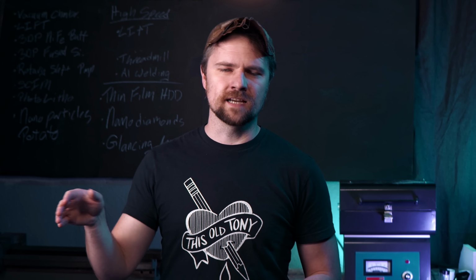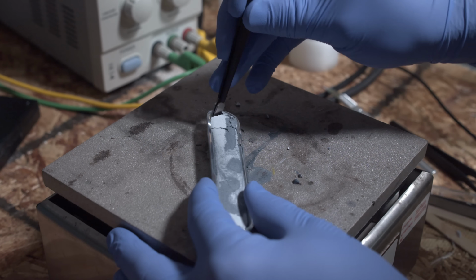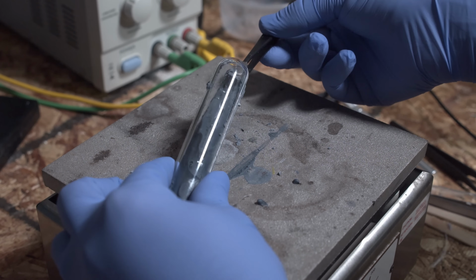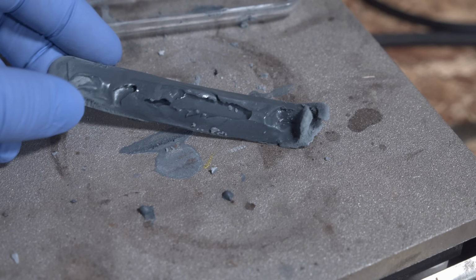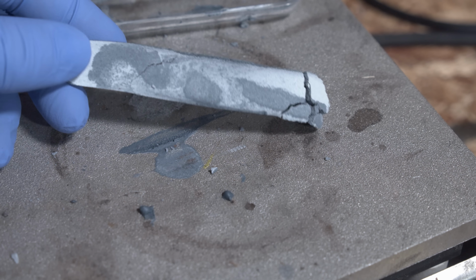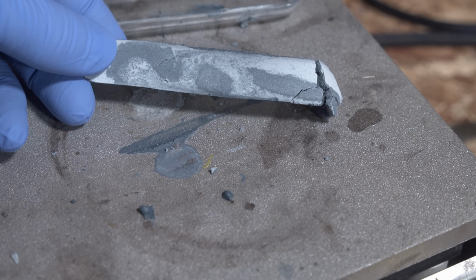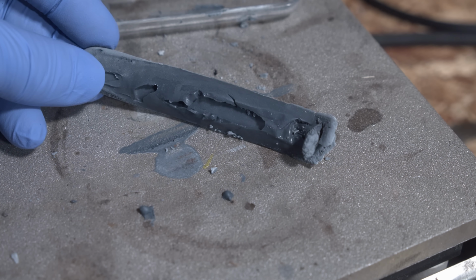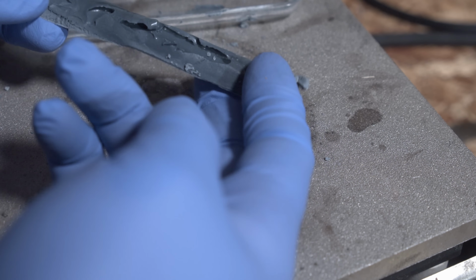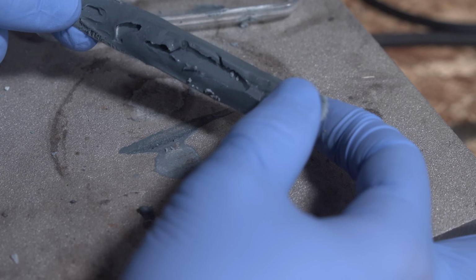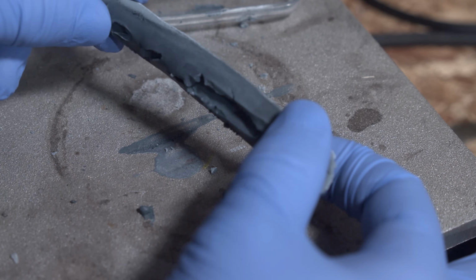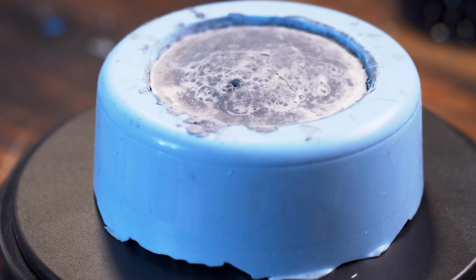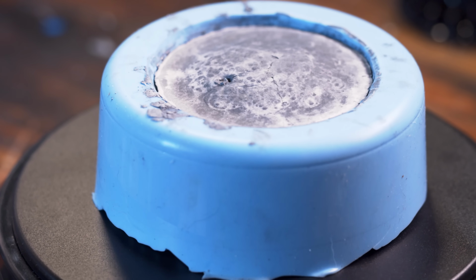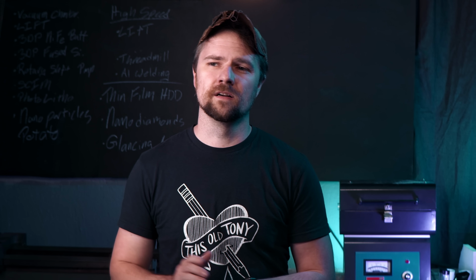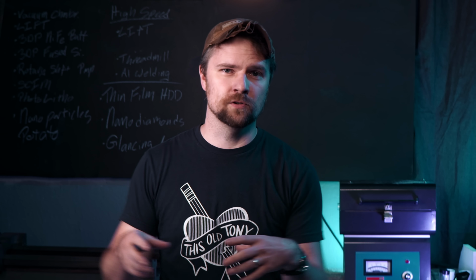What ends up happening is the top surface will form a dehydrated skin while the lower surface stays pretty wet. And even if it gels, it stays really sticky for pretty much every surface that I tried, including silicone. I was using a hot plate at first, but eventually I switched to a food dehydrator, which did a better job. And ultimately I found it was just easier to fully dehydrate the sample for 24 to 48 hours. That made it a lot easier to demold because you had a completely dry part. It has pretty considerable shrinkage too, so it pulls away from the walls of the mold and you can pop the part out a lot easier.